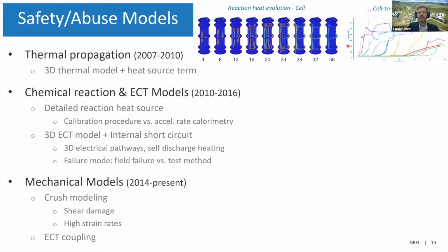And then this carries up to a module or a pack level, and so you can simulate cell-to-cell propagation. Depending on how patient you are to match up thermal contact resistances and such, you can get very tight agreement between the experiments and models. One can imagine that blowing up a pack or a module is a very expensive experiment. After the fact, it's been burnt to a crisp. A lot of times it's difficult to determine the sequence of events, and so models are very useful for helping to determine the sequence of events.